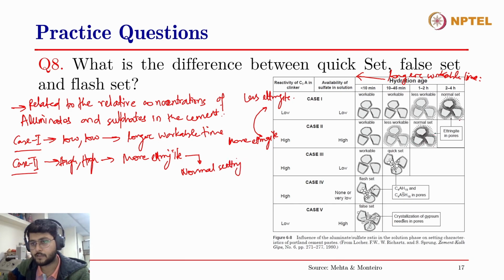So you can see that ettringite is formed in both of these cases, but the normal setting occurs within, let's say, 2 hours, because a large amount of ettringite is getting formed, which is consuming the pore structure, and therefore the setting occurs a little faster. So normal setting but faster.